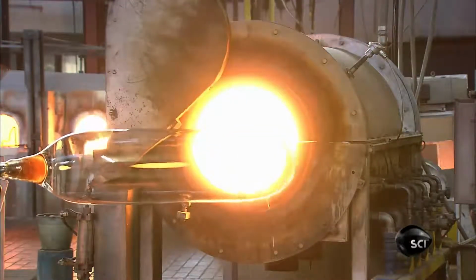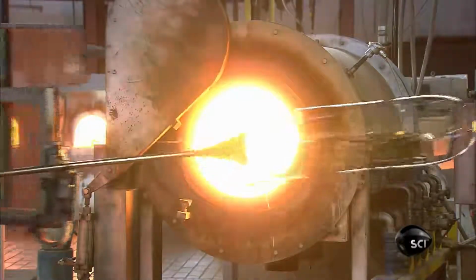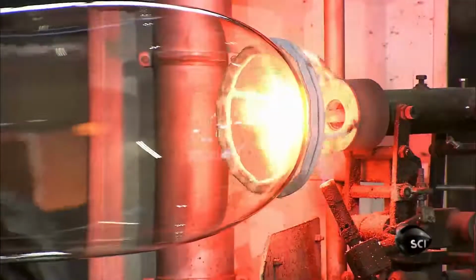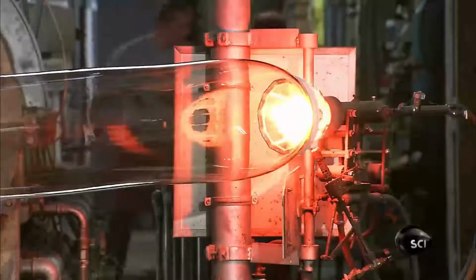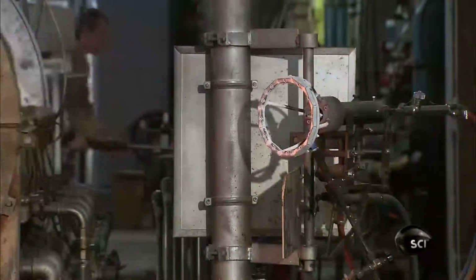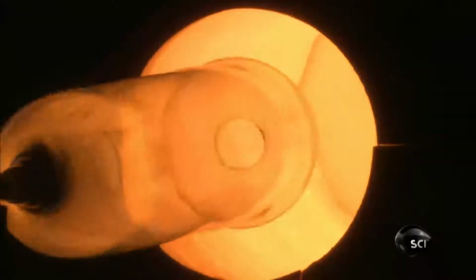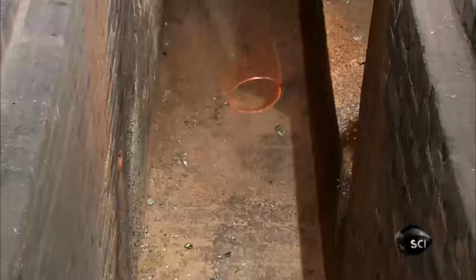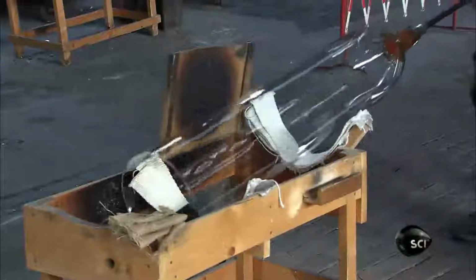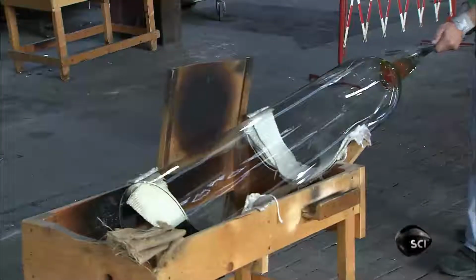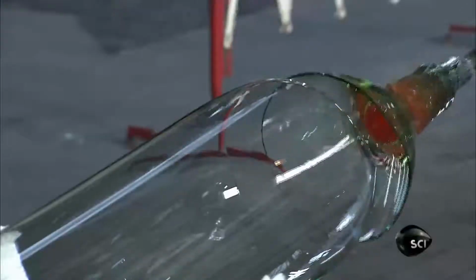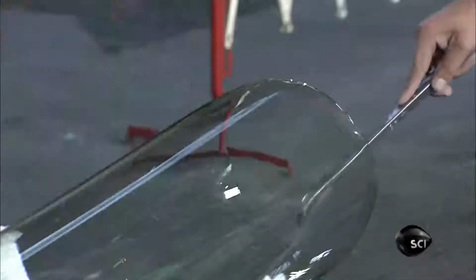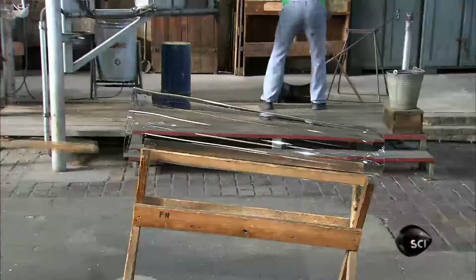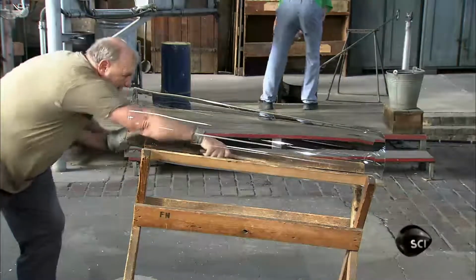He reheats the tip of the glass, weakens the tip with a hot burner, then reheats the entire glass, which expands the air inside, forcing open the weakened tip. The glassblower knocks a cold metal stick against the other end of the hot glass. The thermal shock causes a neat stress break, which releases what is now a glass cylinder from the blowpipe.